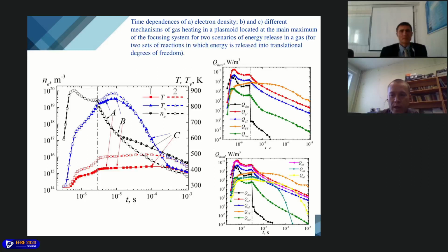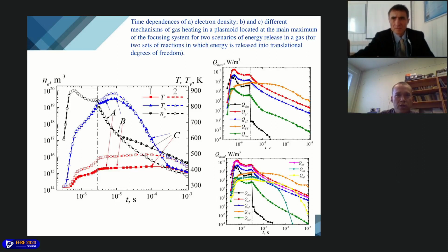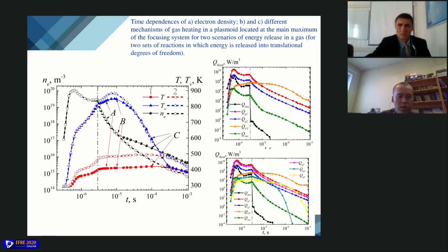Since in practice, in particular in plasmoid applications, the behavior of plasma parameters in the afterglow phase is of interest, let us trace the dynamics of change in the main plasma parameters in the main plasmoid over the entire time scale from 0 to 1 millisecond. The active phase is from 0 to 3 microseconds, and then the afterglow. Here we can see the electron density, the translational gas temperature, and the vibrational temperature for the two sets of fast gas heating reactions.